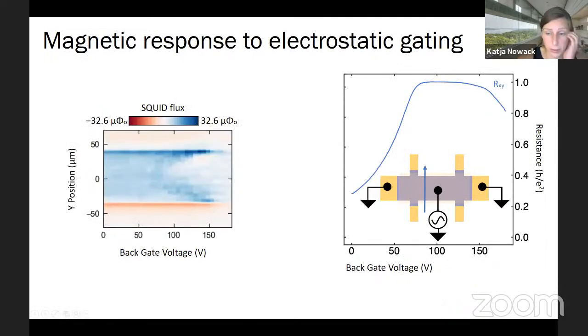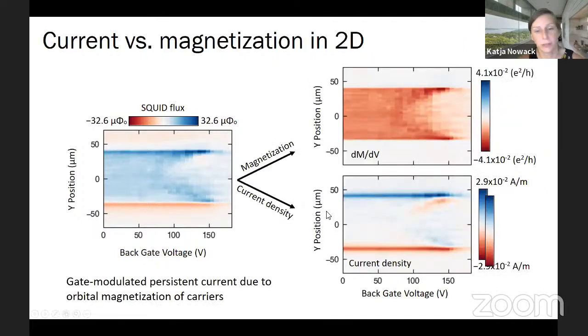We can do this similar to before. We can take a single slice through the device and then continuously tune the backgate voltage. Now we do this over the full backgate range here. And we see that there's a clear evolution in the signal size. We can think about the signal in really two ways. We can choose to reconstruct from our flux signal the magnetization of the device, or I should say a change in magnetization in response to the voltage that we apply, which is shown here.